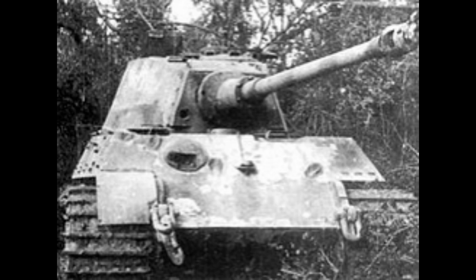Soviet metallurgists compared Tiger II armor composition to specifications for standard armor steel. The deficiencies were systematic and severe. Without adequate nickel, the armor became brittle at low temperatures, exactly the conditions prevailing across the Eastern Front during winter operations. Without sufficient molybdenum, the steel lost strength under sustained high temperatures, precisely the conditions created by repeated shell impacts. The substitution of manganese for superior alloying elements produced armor that met thickness specifications, but failed to provide equivalent protection.